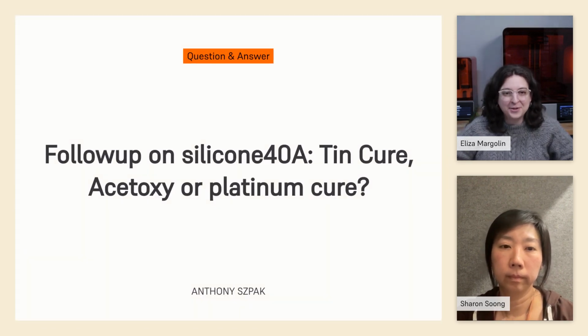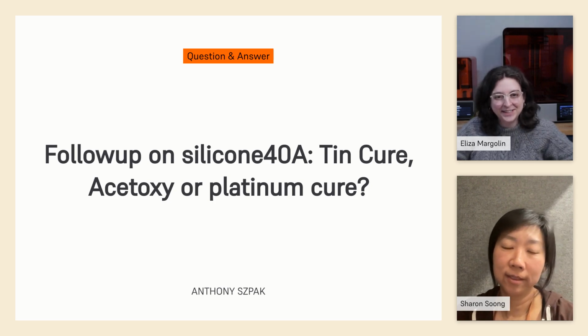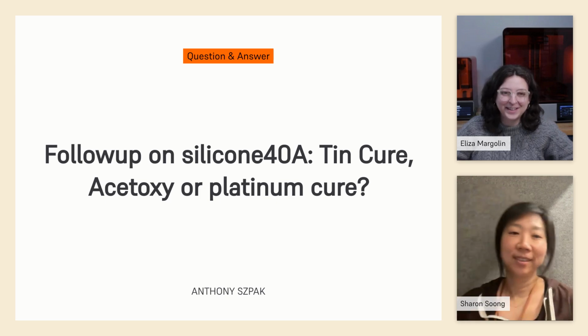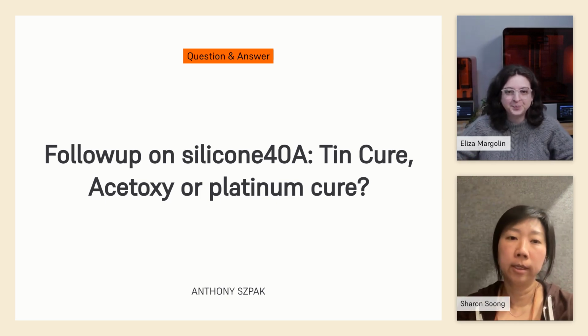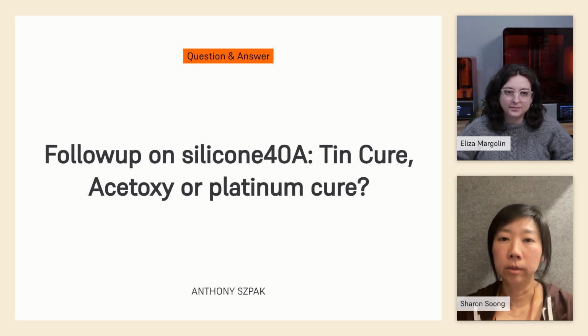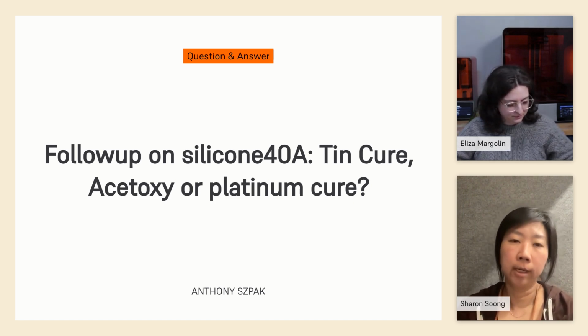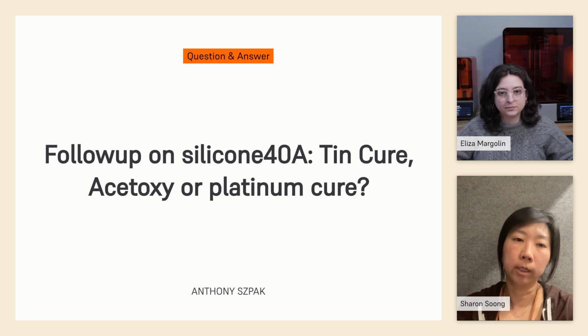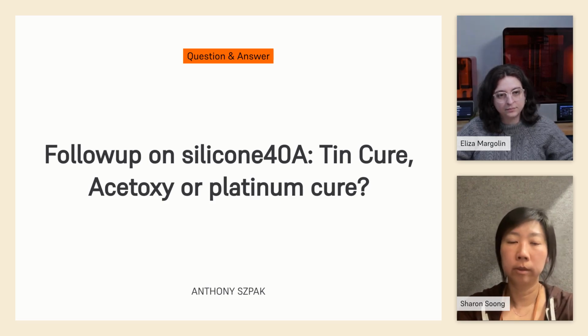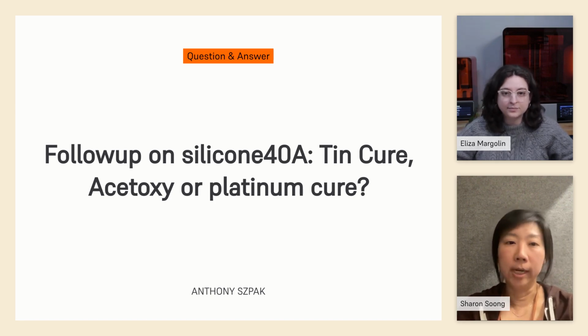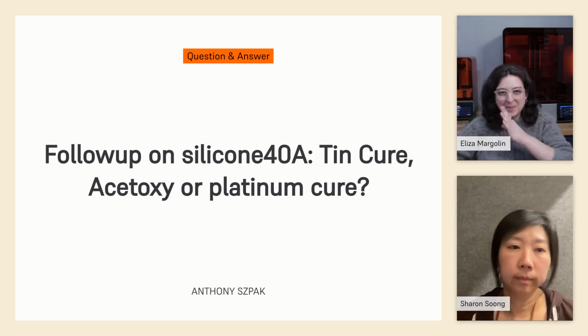Follow-up question on silicone 40A. What kind of cure? None of these. Trade secret? Oh, it's in the patent. Okay, yeah, it's still photo cure. There's a photo inhibitor in it. We were able to find a way to get the cross-link reaction to happen fast enough in the printer. Photocurable silicones do exist, but they typically take a long time and a lot of light, which makes it really hard to make them work in our printer. But we were able to find a chemistry pathway that allows it to work in our printer. We had to make some compromises, but for the most part, it's a true silicone. It performs very much like a true silicone, and you can print it in any shape that you want now. So yeah, it's none of these. And check out the patent.